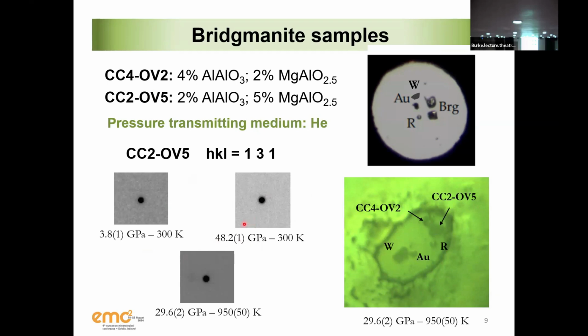What I also want to show you is that, of course, this is a beautiful loading. And then when you start to compress and heat, we have helium, which is very, very soft, and therefore your gasket will just collapse and will be really deformed very much. Not only that, but when you start to heat up, helium will become liquid again, because at those pressures, above 10 GPa, it is solid, but at higher temperature, it will become liquid again. And then you start to see your crystal moving. So it is really a game of, let's wait long enough until everything is stable, then we take a picture, then we center the cell, then we try to find the crystal, then we collect the data.